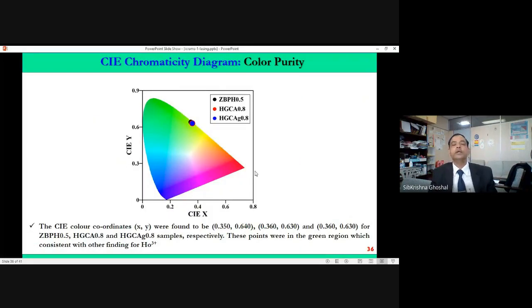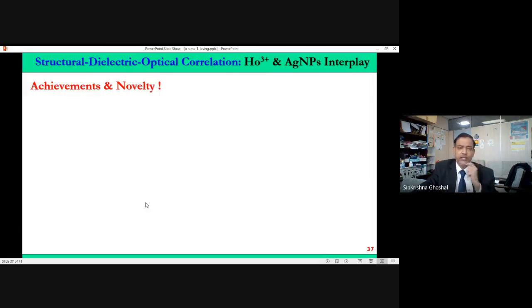But the last thing we want to check is, what is the purity of this color? So we have wide green, because we know in the visible spectrum, green can be several wavelengths. Red can be several wavelengths. Yellow can be several wavelengths. But which red wavelength? Which green wavelength? That means the monochromaticity and color purity can only be checked by the chromaticity diagram. This is called the CIE chromaticity diagram, and these are the coordinates for the chromaticity. When we check, we see the color purity for red and green is quite interesting, and that's what we wanted, and we achieved the target for the time being.